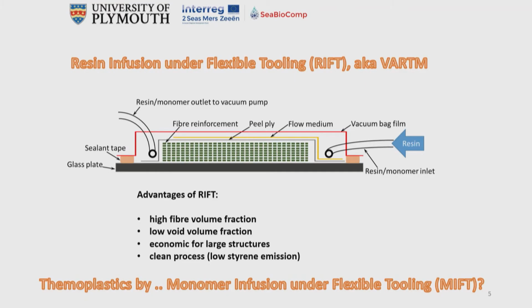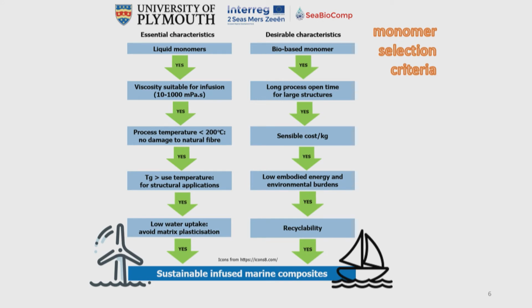But thermoplastics, the melt viscosity is far too high to get it to flow in an infusion process. But if we start from the monomer and make the polymer at the same time as we make the composite, we can potentially do monomer infusion under flexible tooling. In order to do that, we need to pick a monomer that suits a variety of characteristics.